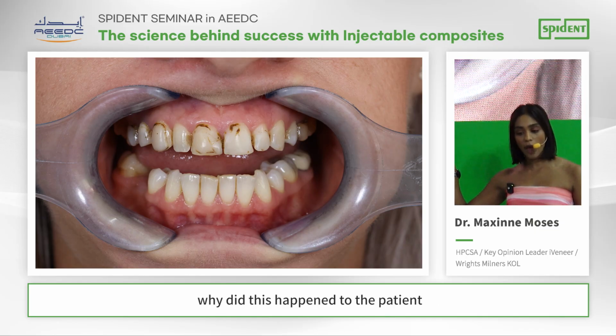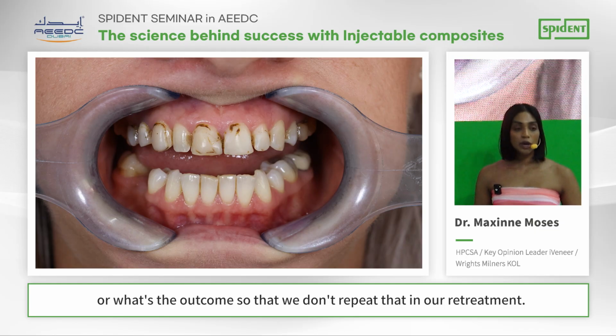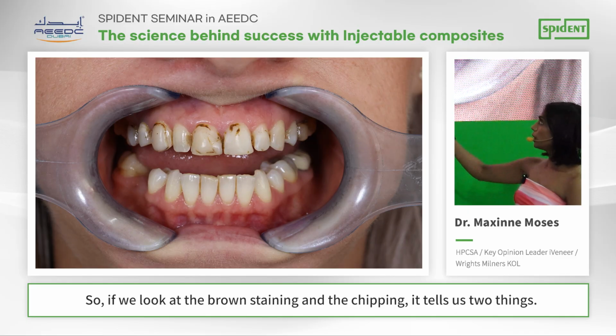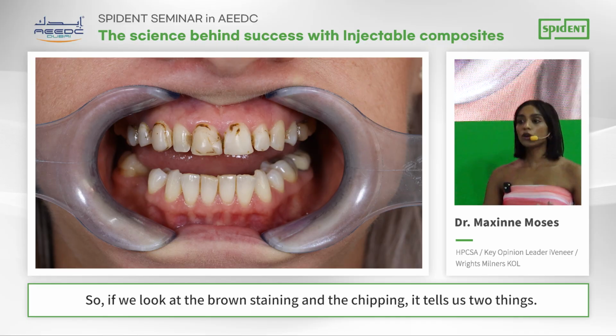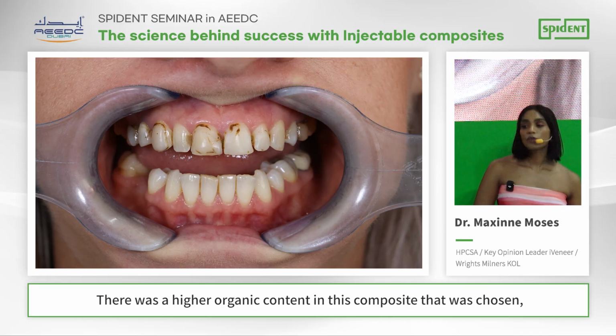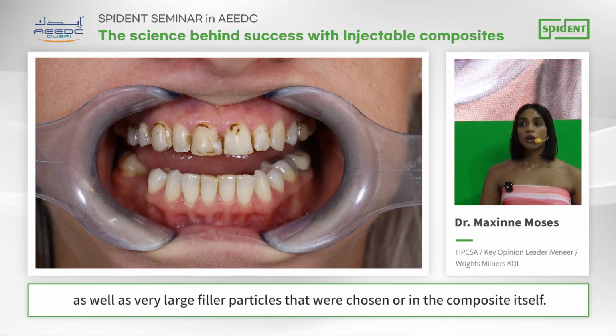Why did this happen to the patient, so that we don't repeat that in our retreatment. So if we look at the brown staining and the chipping, it tells us two things. There was a higher organic content in this composite that was chosen, as well as very large filler particles in the composite itself.